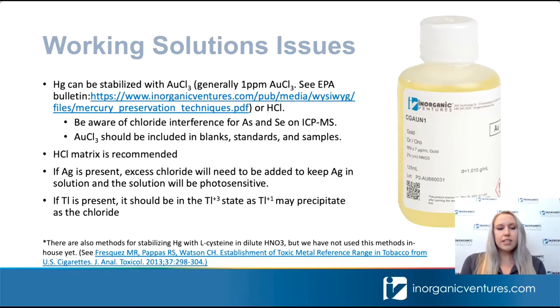Another option is to add hydrochloric acid to the matrix, and this is the option that we generally recommend for stabilizing mercury. Some additional concerns do come up with using HCl as the matrix. So if you have silver in your solutions, it is going to precipitate with trace chloride. So you will need to add an excess of hydrochloric acid if you do have silver in the solutions to prevent that precipitation. And also, these solutions are going to be light sensitive, so you want to keep those away from light to prevent the photoreduction to the silver chloride precipitate.